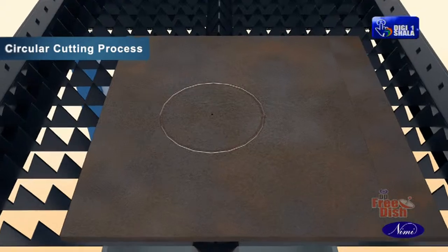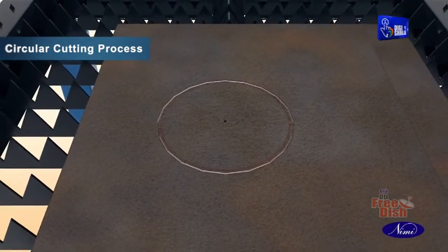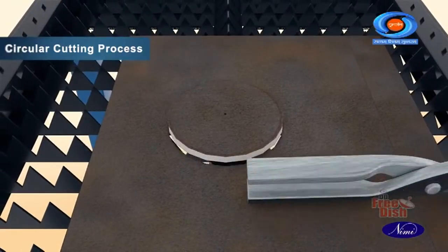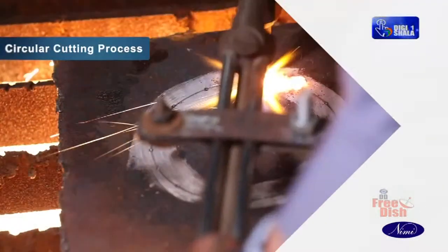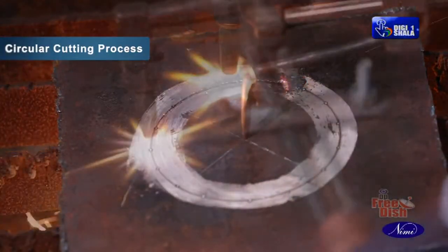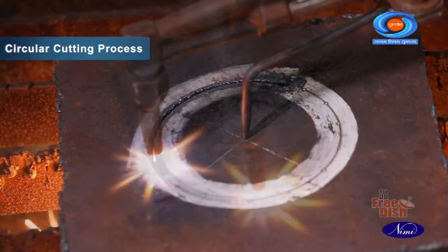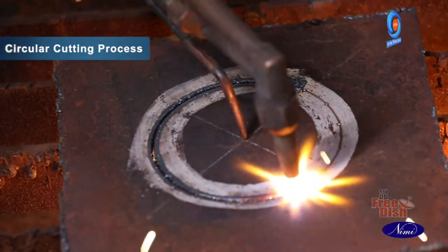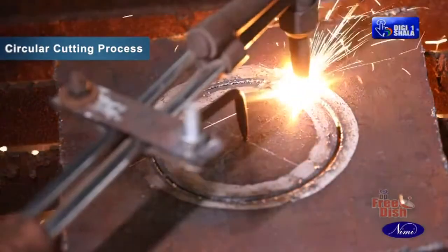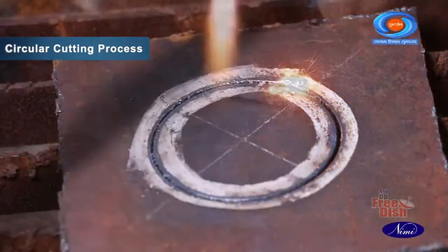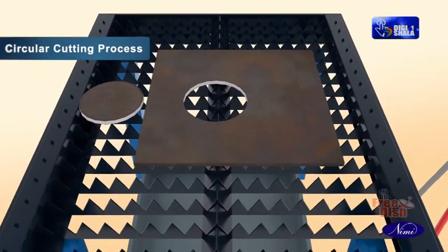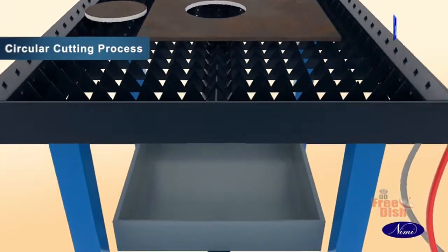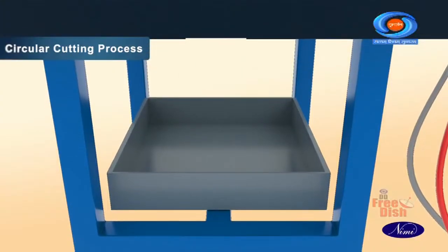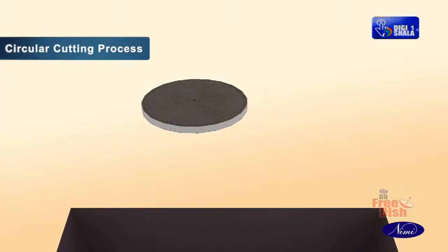After the cut is over, remove the slag from all the gas cut surfaces. Ensure that the molten slag and solidified hot slag that are chipped fall through below the table. Inspect the cut for gas cutting defects.